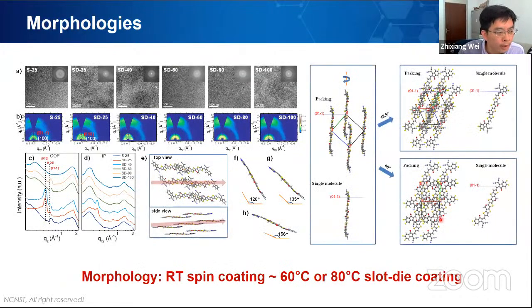The reason behind that is the morphology for spin coating and slot die coating is quite different, because spin coating is a really fast drying process. But for slot die coating, all the solution is there, and the drying process is quite slow. Therefore, we need to increase the substrate temperature. And finally, we can get a similar morphology using slot die coating at 60 and 80 degrees. The morphology is quite similar to spin coating at room temperature. The molecular arrangement on the substrate is vertically aligned, and in this direction they have a better charge transport pathway.